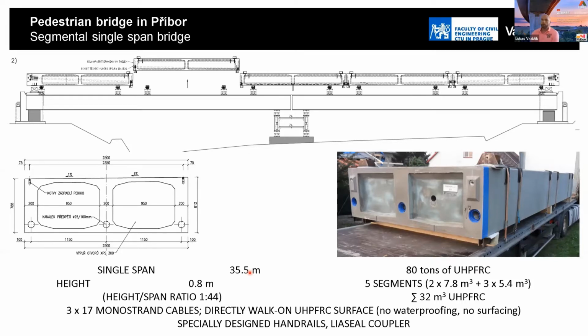As I said about the disadvantage of the UHPC, it is necessary to produce precast elements. So in this case, the superstructure was divided into 5 separate precast elements: 3 normal elements, which were situated in the middle part of the structure, and 2 side elements. The geometry of the elements was the same, only in the side elements, which are situated above the abutments, there were some changes in the thickness of the outer walls. The reason was that we have to produce the anchorage of the prestressing tendons.